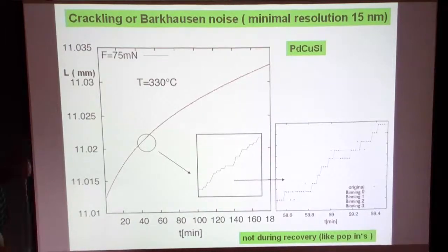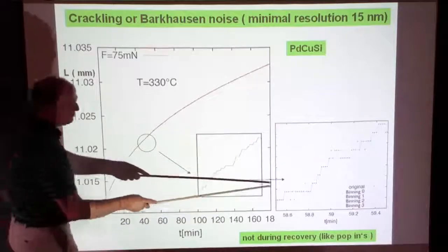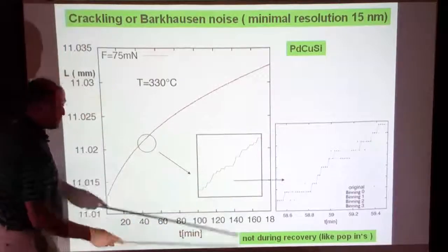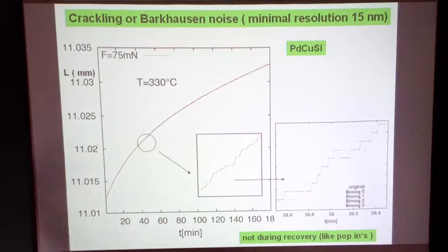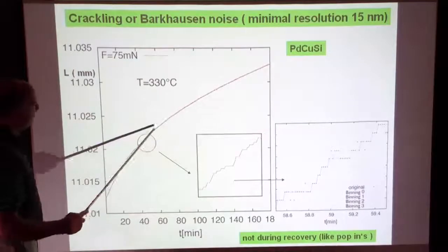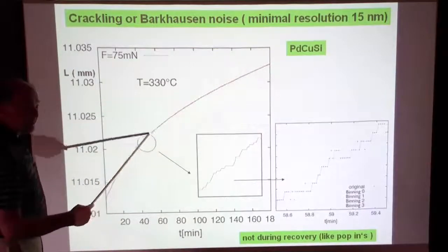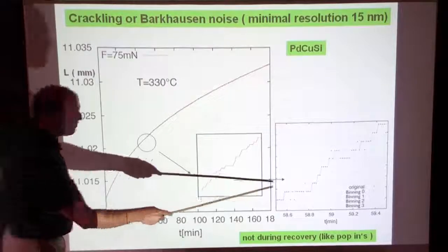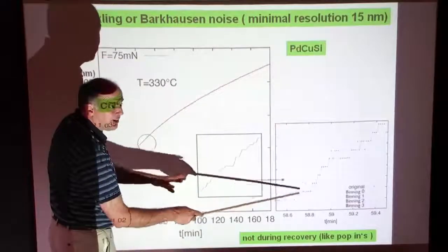We have the waiting time analysis. There is a fine structure which we don't see in the other. Yes, this is the fine structure. The overall curve looks like that. If you look more closely, you see that, and if you look even closer at that one, there is a fine structure. This is a minute, so we have much more fine structure in there.